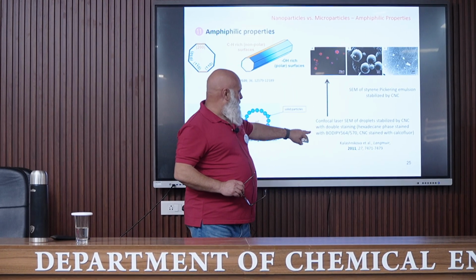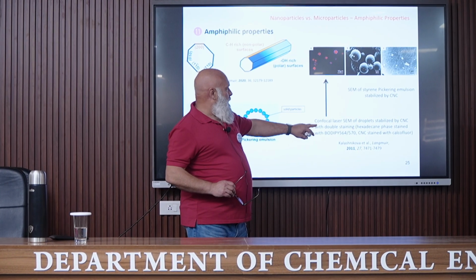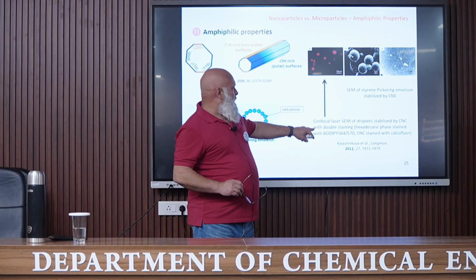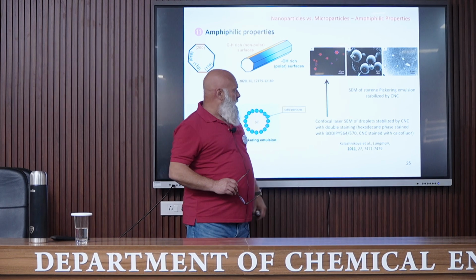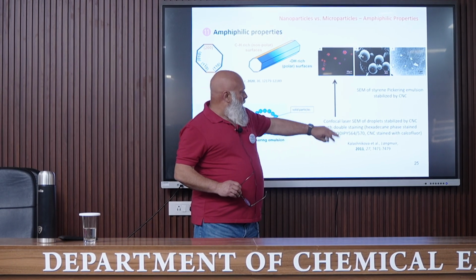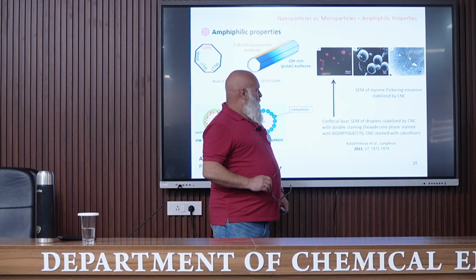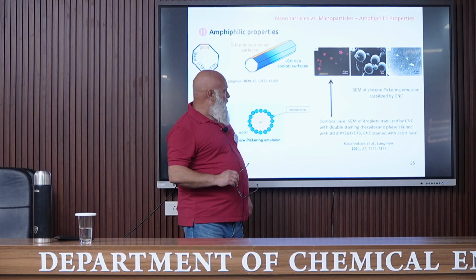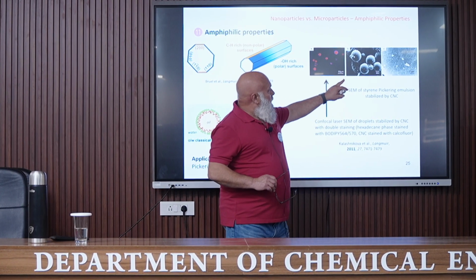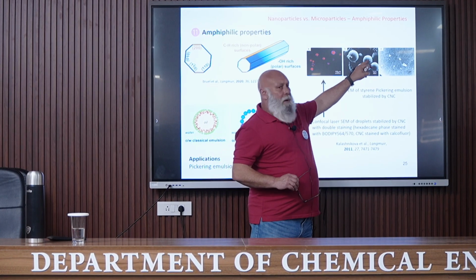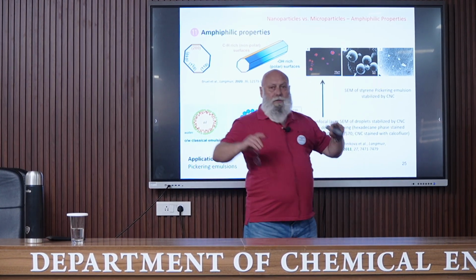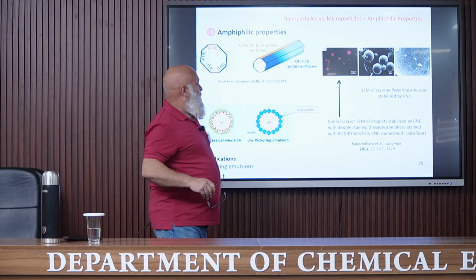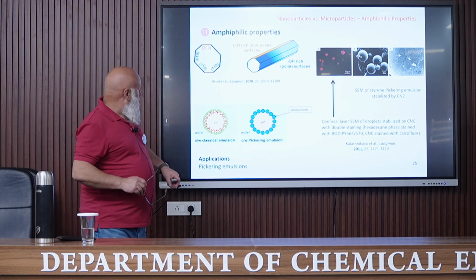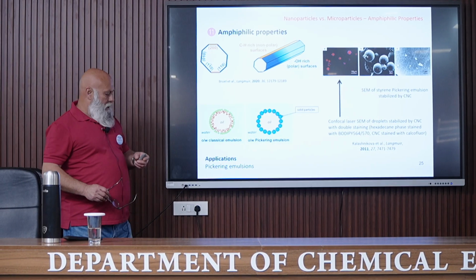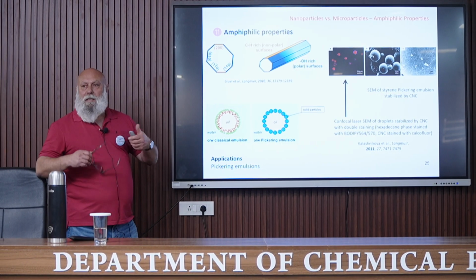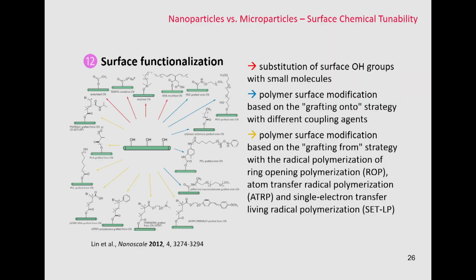So on the left side, maybe we can check here, it's a confocal laser image of a droplet stabilized by CNC with double staining. So it was cellulose and hexadecane was stained with a different component. We can see here the SEM observation, so the droplet of oil, and we can see the cellulose nanocrystals on the surface of this droplet. And of course, the possible application is for Pickering emulsion or detergent and so on. Surface functionalization.